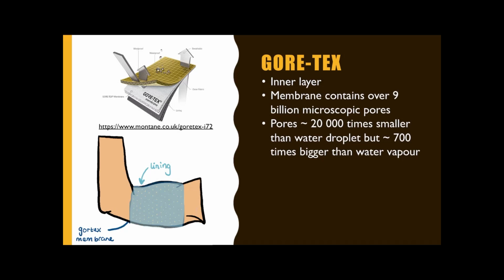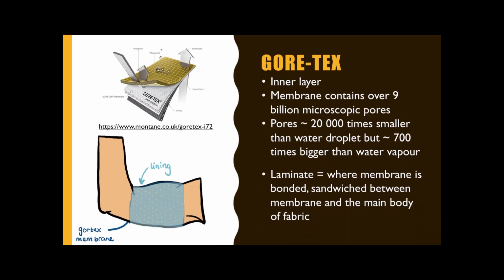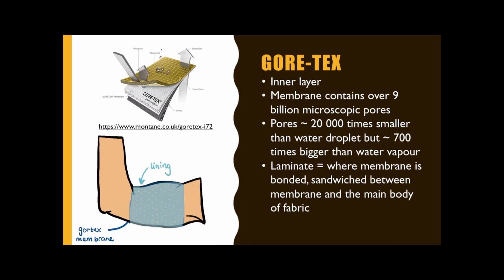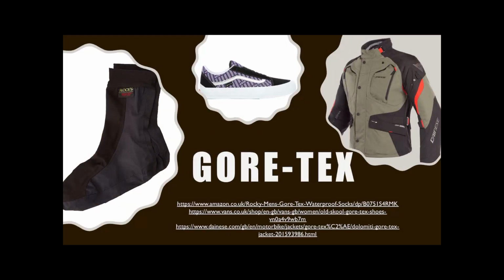The membrane contains over 9 billion microscopic pores, which are about 20,000 times smaller than water droplets, but actually 700 times bigger than water vapor. This allows sweat to evaporate off the surface of the skin, but doesn't allow water to actually penetrate through the fabric. The laminate is actually a fusing, and then the outer layer is for comfortability and for visual appearance, so it's usually nylon. It's used for socks, shoes, and outdoor apparel such as coats.